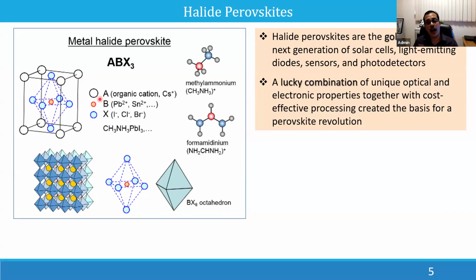because you can change the anion or cation and you can get an array of properties. So instead of oxygen, people started using halide anions, and they found that these, especially iodide, chloride, and bromide, are very suitable for this kind of structure, except fluoride. Fluoride is very small in structure, and it cannot give a very stable perovskite structure. So they started working on ABX3 instead of ABO3.